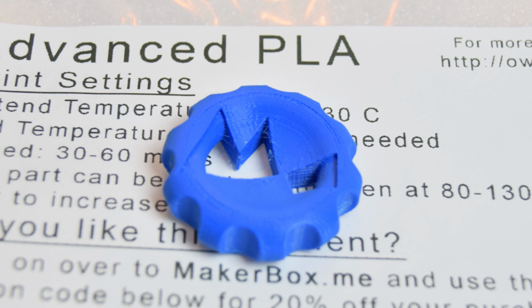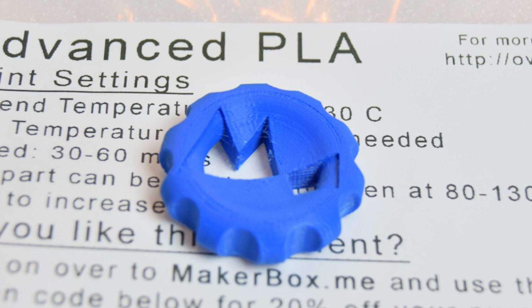I used the Up Box, and I set the temperatures to 230 degrees C, which is quite hot for PLA, but the Up Box seems to work better at hotter temperatures. I don't know why, but the results are great. There is a little bit of stringing, and again, that's probably the higher temperature I used. But in terms of the infill, it's fantastic, and the part works great. So this is going to be a very nice premium PLA for anyone wanting parts that look really good and have a higher strength, but you need to do the annealing process, which I have not done for this, but it's something I'm going to try in the future.